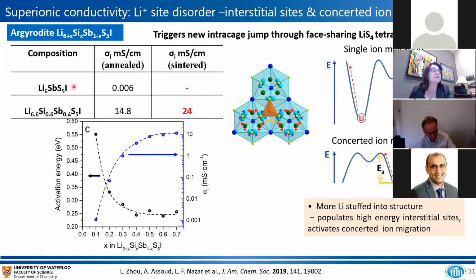So this argyrodite is actually a material which has fundamentally very poor ionic conductivity. And it has an unusual structure, which is comprised of clusters of lithium ions. And I won't get into all the structural details because it's too much detail for such a talk. But the point is that if you start off with this parent material, the lithium is bound up in these little clusters, and it doesn't undergo translational hops from one cluster to the next, which is why it has such low ionic conductivity. If you substitute some of the antimony +5 for a combination of silicon +4 and lithium +1, which is effectively tantamount to stuffing the structure with lithium, now conductivity is on the order of 15 millisiemens and above, depending on whether it's annealed or sintered.